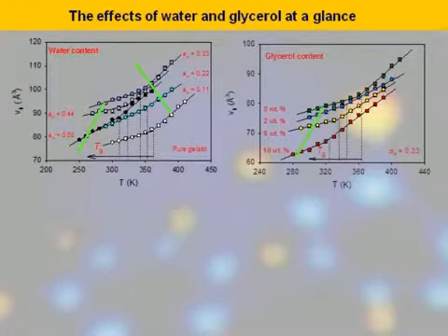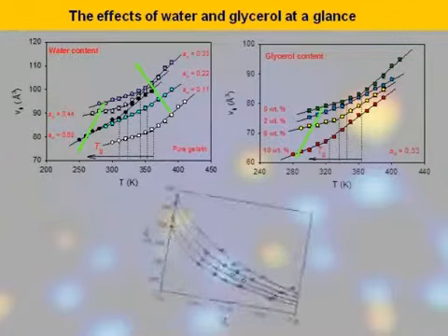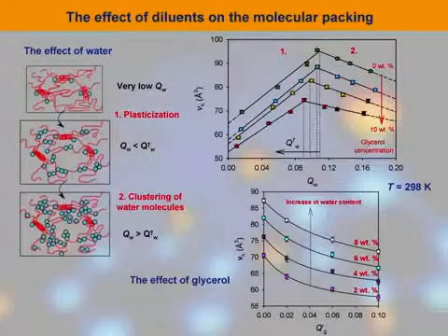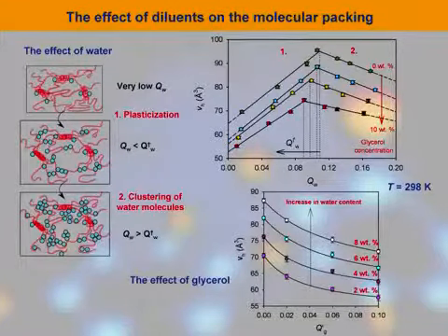Both molecules significantly reduce the glass transition temperature of the matrices, and this plasticizing effect may be modeled semi-empirically by using the Gordon-Taylor equation. In the glassy state, we observe a rapid increase in the hole size of the gelatin matrices as a function of increasing water content. The water molecules plasticize the gelatin matrices by binding to the polar side groups of the polypeptide chains.